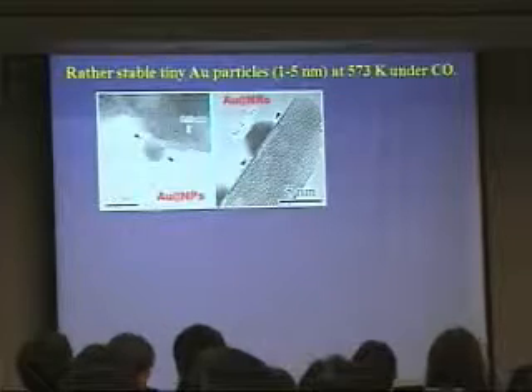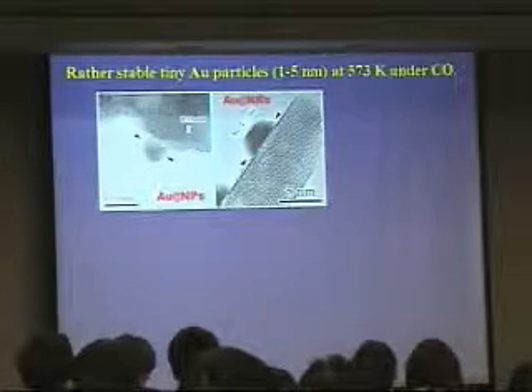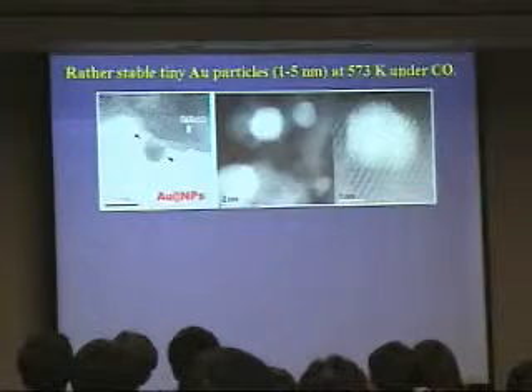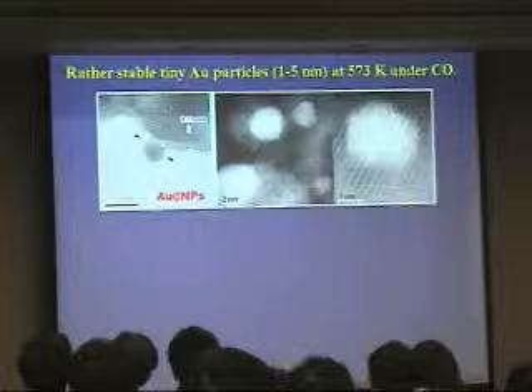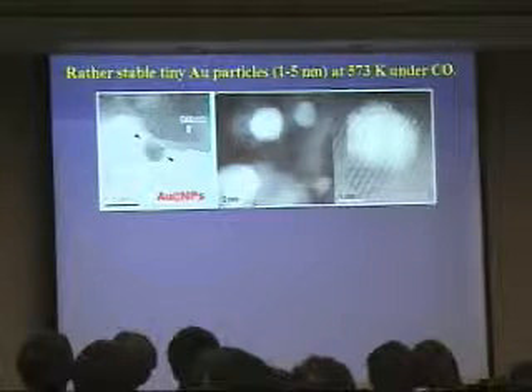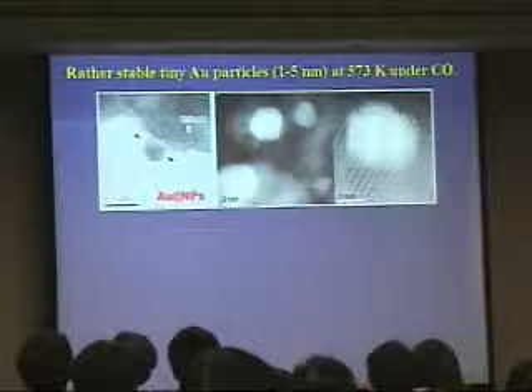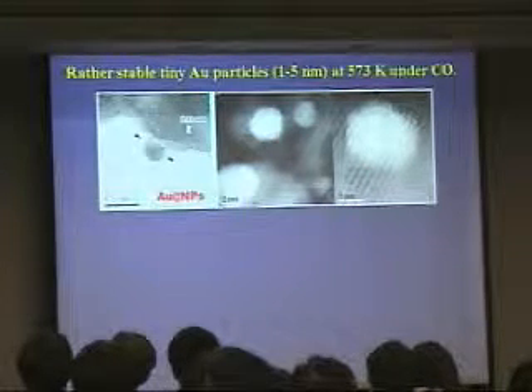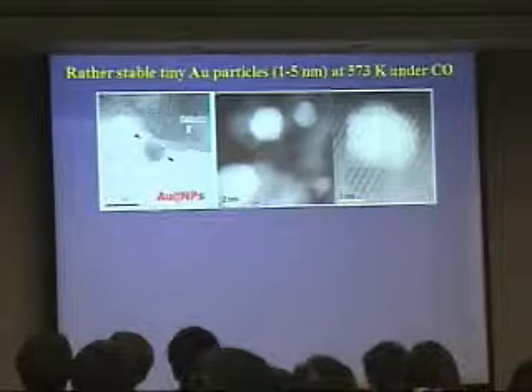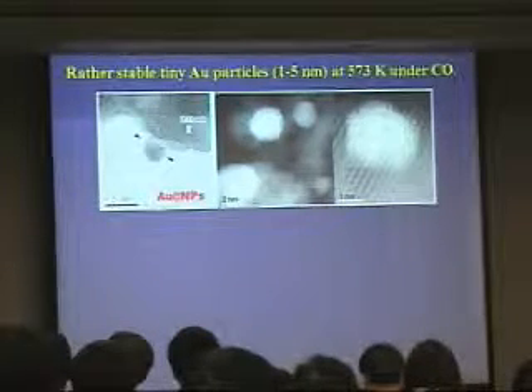But for this kind of interface with spherical particles, if exposing the 111 surface with gold, you can find the surface is not so tight. But if we change the shape of this support into rod shape, you can find the contact becomes very tight. And the shape of the gold particle is also changed. If we go into more detail to see their interaction, you can find the gold atoms are already deeply incorporated into the lattice of ceria. So this makes the bonding of the gold particle and the ceria support very strong.